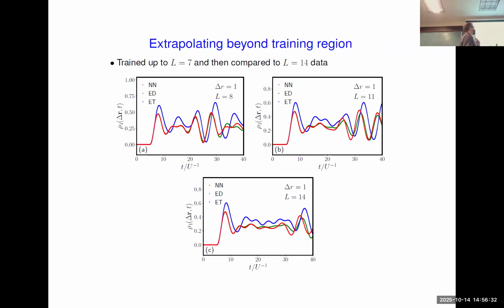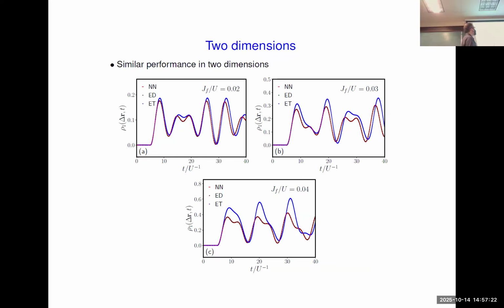And we actually tested extrapolating beyond the training regime a little bit more. So we trained on a restricted data set with only up to L equals 7, and then did a comparison with L equals 14 data. So now we're looking at a system that is twice the size of what we trained on. And it's not quite as good as when we trained up to L equals 11, but it's still a massive improvement on our inputs. So we hope that this might be useful for strongly interacting quantum systems where you're restricted in what you can calculate exactly, but you have some decent approximate theory.